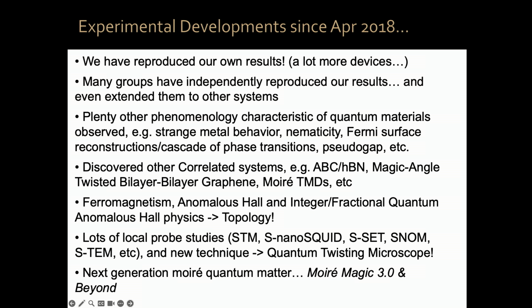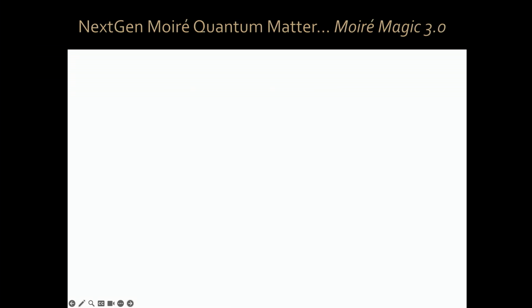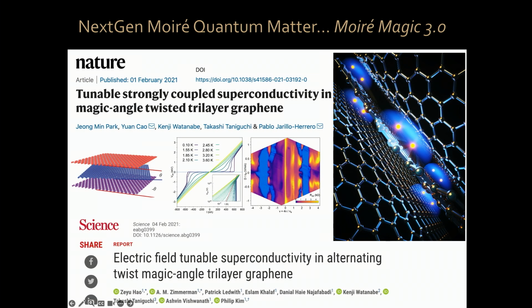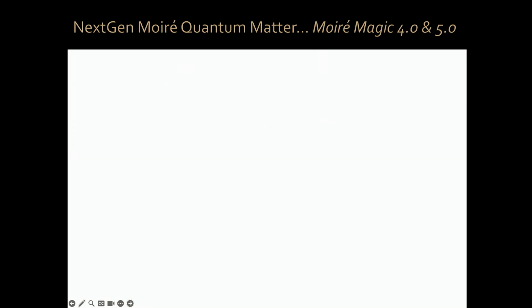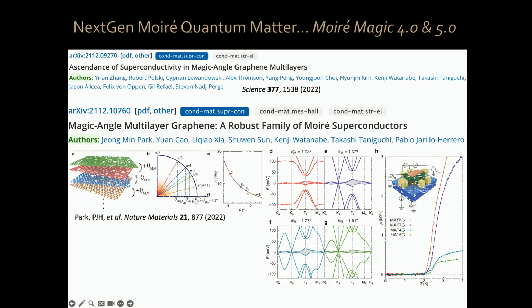In particular, in 2021, the group of Philip Kim, who was my postdoc advisor and is a professor here at Harvard, and my own group reported back-to-back papers in Nature and Science with the discovery of magic angle twisted trilayer graphene, which turns out to be an even better and stronger superconductor and more tunable than the bilayer. The following year, 3 groups, the group of Emanuel Tutuc at UT Austin, my own group, and the group of Stevan Nadj-Perge at Caltech, showed that magic angle tetra and pentalayer graphene are also robust superconductors. So now we have a family: 2 layers, 3 layers, 4 layers, 5 layers. That's enough members that we can call it a family.